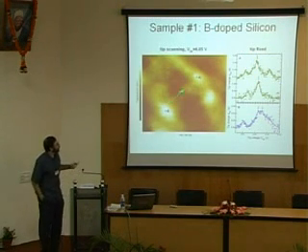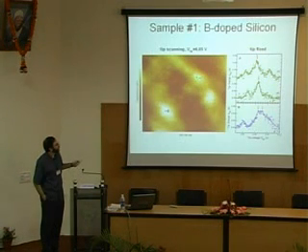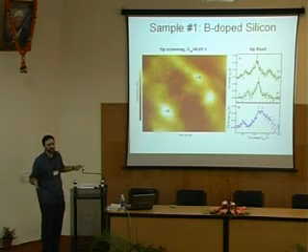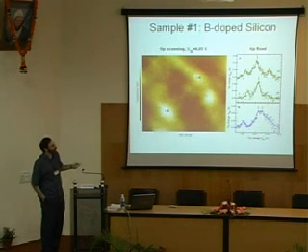And actually what we're seeing here at position A, we see not one but 4 peaks, and we believe the peak that corresponds to the dopant right below position A gives us the taller capacitance peak, single electron peak. But there's also dopants that will tunnel into these other areas that are a little bit farther away. If we go to a higher voltage, we get the electron to tunnel there. It also gives a capacitance peak, but now it's reduced magnitude because the data was taken with the tip here. If the electron's going to tunnel over there, a smaller percentage of the electric field hits it, and that's why the peak is lower. We think we understand that.